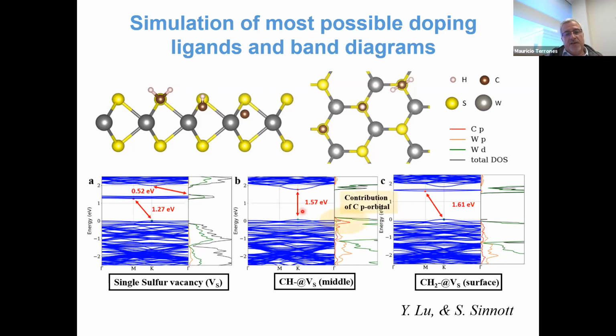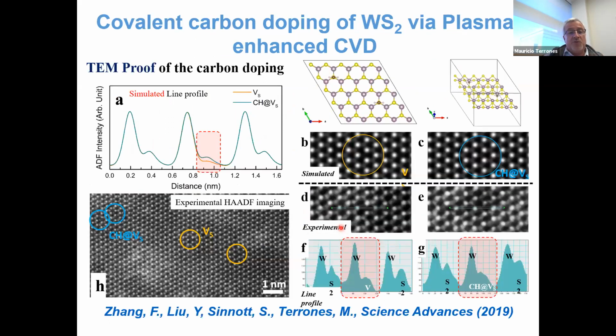So then you have contribution of the carbon atoms here in the valence band. And so what do we see in electron microscopy? In electron microscopy, we see this is a sulfur vacancy, but maybe you don't see it, but the sulfur vacancy is there. So there's one sulfur missing. And this is the replacement of the sulfur vacancy by a CH group, right?